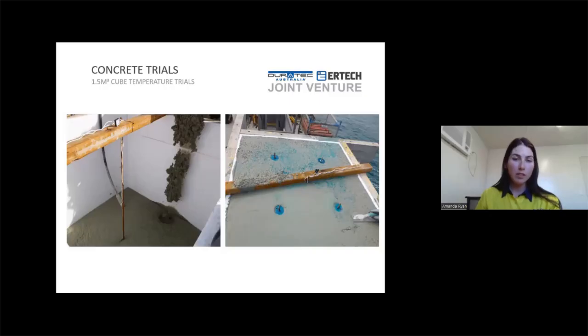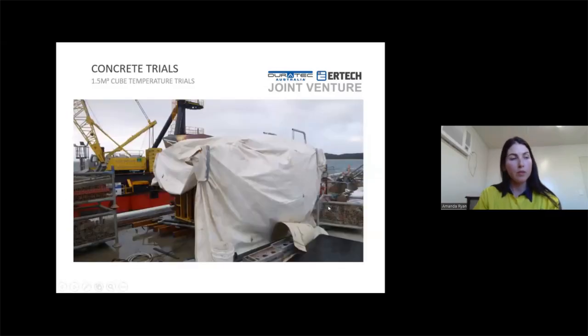So here we have insulated forms. We did a 1.5 by 1.5 cube with insulated forms, single ply in the bottom, and the sides were insulated with expanded polystyrene sheets. Temperature probes were installed, the top was cured with aliphatic alcohol, which is this blue liquid, and then trowel finished, which you can just see here. And this is the curing: we left it to cure for 14 days with water running for 14 days. So our water cured.